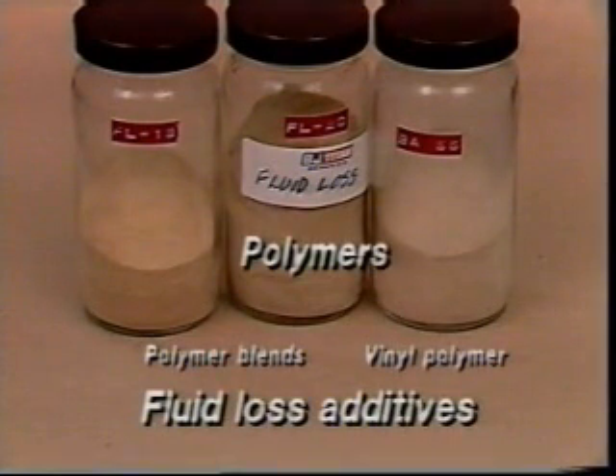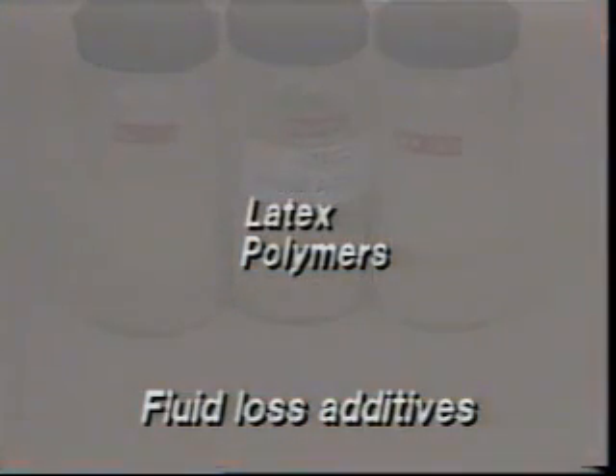Fluid loss can be controlled with additives such as organic polymers, which form micelles or films that contain the liquids within the slurry, and latex, which forms a film that causes the slurry materials to adhere to one another. The goal of fluid loss control is to keep that fluid loss to less than 100 milliliters. Chevron believes in controlling the filtration rate on its primary production cement jobs to less than 100 mils in the standard API 30-minute test and to less than 50 mils in a liner test, because empirically they found that those results give them the best primary cementing success ratio. In other words, the least amount of remedial work.